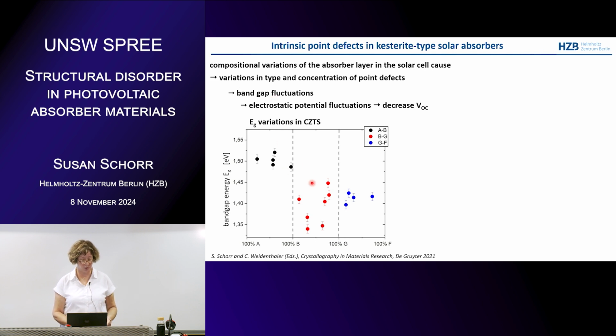Because this is shown here in copper zinc tin sulfide, if you go from A type to B type to G and F, and this is the bandgap, you see that the bandgap changes. And because of that, you will get electrostatic potential fluctuations, which then will decrease your open circuit voltage.